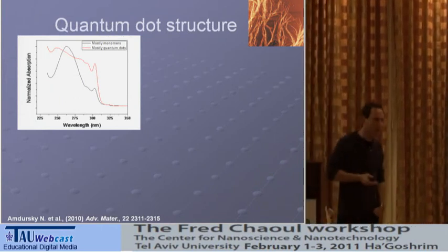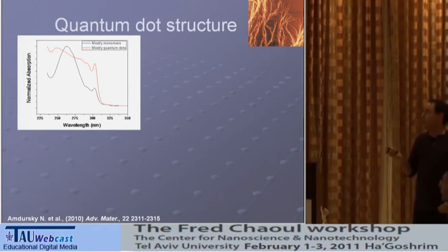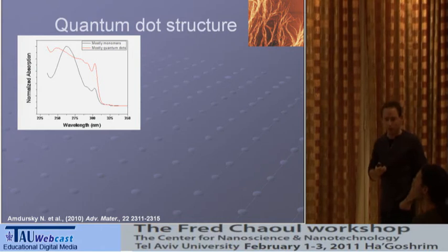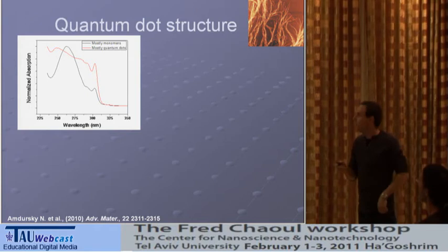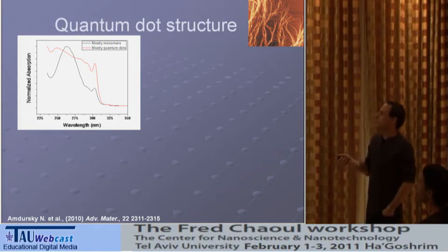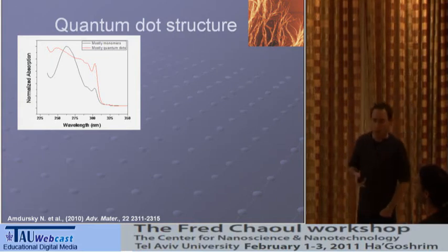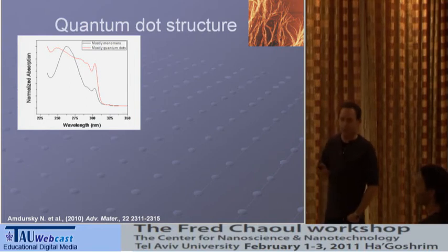One of the basic measurements we can do with optoelectronic structures is an absorption spectrum. This is the regular absorption spectrum of these spaghetti-like structures. And I found right in the beginning a somewhat interesting phenomenon. You can see here two graphs. This is the same material. I'm using the same powder for this graph and this graph, but this is in low concentration, and this is in high concentration. In low concentration, I cannot get those structures, and in high concentration, I can get these structures.